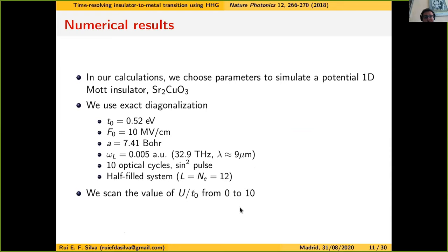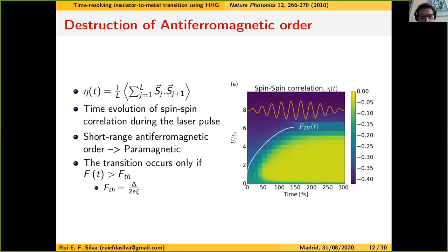So what we are going to do now is to solve the 1D Hubbard model using exact diagonalization, and we are going to shine a strong laser field and see what is the high harmonic response. For that, we have used parameters to simulate this 1D Mott insulator. And what we are going to do is to scan the value of U. So we are going to do several calculations from U equals 0, that is a pure conducting system, to U equals 10, that is a pure Mott insulator. So what we see